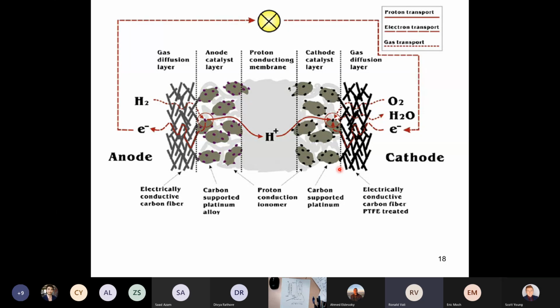Would a very vague, simplistic answer be that it's because of its unique electronic structure compared to other elements? Yeah, it's a unique electronic structure. Also, it's a noble metal. So that means that its surface is generally platinum metal. And that's not always the case when the fuel cell voltage becomes large. The surface gets covered with platinum hydroxide and platinum oxide, which then limits its activity. So when the fuel cell voltage goes down again below about 0.8 volts, all those species are stripped off the surface, and then the catalyst reaches its full activity. So it has to be noble, and its electronic structure has to be right.